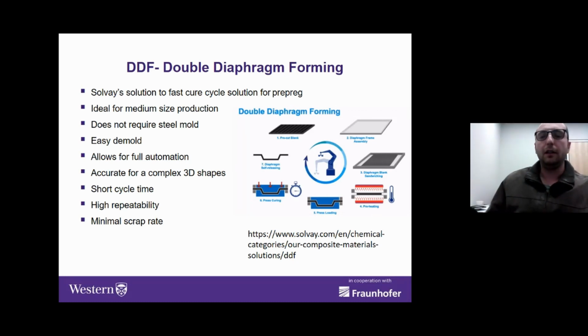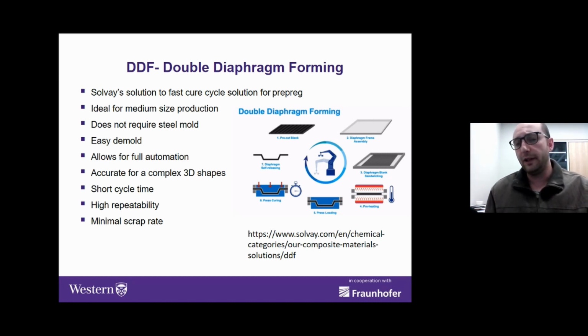The other good thing that it does is that a big problem we see in processes like HPRTM and LCM is the investment in the mold. So the mold in this process can cost up to $1 million very easily. And so for a medium scale application, if you don't want to do hundreds of thousands of parts, investing in a mold like that is very problematic. In case of a DDF, it's a fairly simple mold. It can be, again, aluminum mold. The problem that we see in aluminum used in liquid compression molding or HPRTM is resin sticking to the mold, and then there is actually no way of getting rid of it without damaging the mold. But in this case, because there is no direct contact of resin with the mold, it's not a problem, and you can use a much cheaper mold to make your parts. So it looks like a very attractive process.